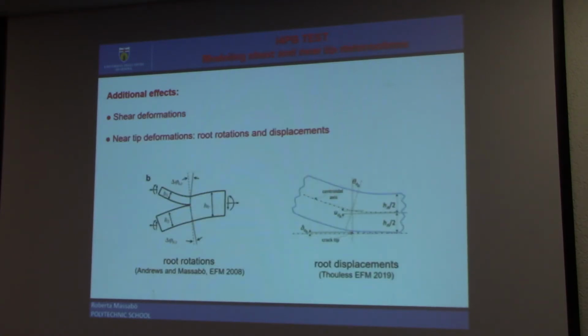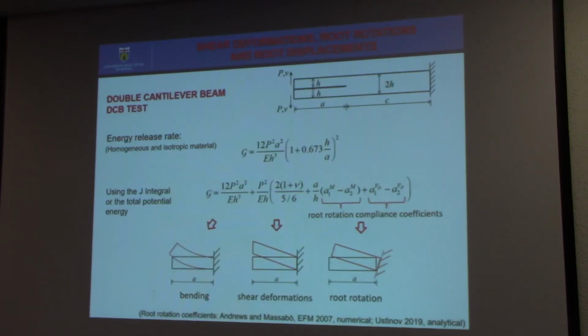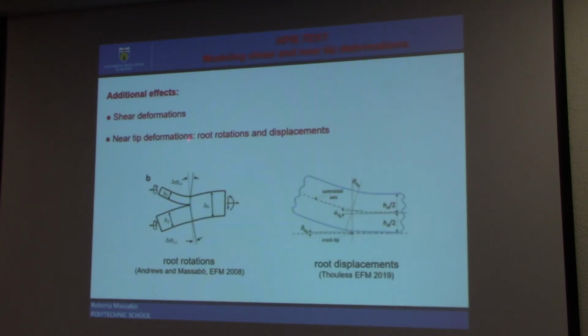For shear, we simply use the theory of a shear deformable beam to solve the problem. And for the near-tip deformation, we decide to use the concept of root rotations and root displacement. So what are the root rotation and root displacement? Root rotations are essentially relative rotations of the crack tip cross-section of the different arms of the specimen. And this relative rotation arises due to the compliance of the material ahead of the crack tip.